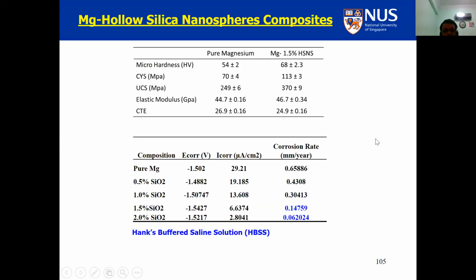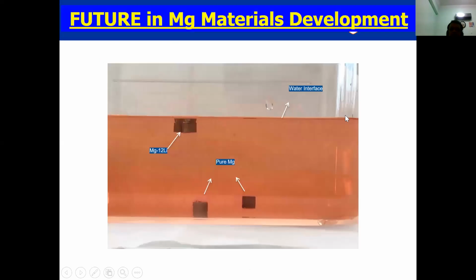We also tried hollow silica nanosphere, and obviously it improved the properties as we have seen many times before, and it can also give us a very low corrosion rate. So once again, remember, silica is called bioglass. It can be used in the human body. So where we are heading now, we are trying to improve all these facets to make magnesium a better material in both body and in engineering application.